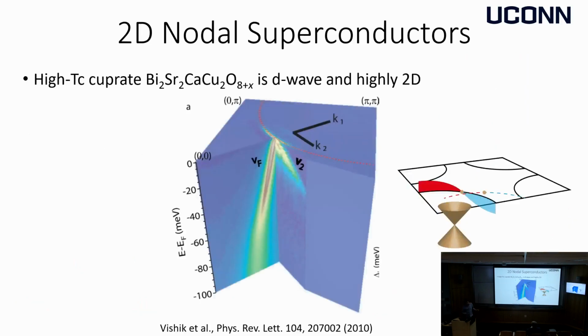There's also, of course, experimental motivation. So this Dirac cone can be basically directly visualized with angle-resolved photoemission in the superconducting state of so-called BSCCO, which is one of the high TC cuprates. And I think this beautiful figure really illustrates the correspondence between theoretical expectation and what you see in experiments. So there's a linear dispersion in both directions. The red line is the Fermi surface. So both perpendicular to the Fermi surface and along the Fermi surface, you see a linear dispersion, which characterizes a Dirac cone. Importantly, unlike graphene, this is a very anisotropic Dirac cone. Those two velocities are by no means the same, and they're actually an order of magnitude different.